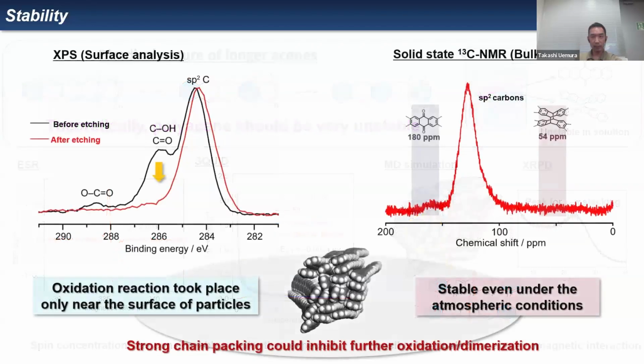Okay, so next we carried out the XPS of this polyacene and found that the oxidation reaction took place only near the surface of the particles. I mean, the inside of the particle is stable. So only the surface of the particle was oxidized like this. This is probably because of the strong chain packing. Strong chain packing could inhibit further oxidation or dimerization inside the particle. That's why the polyacene obtained here is stable even under atmospheric conditions.